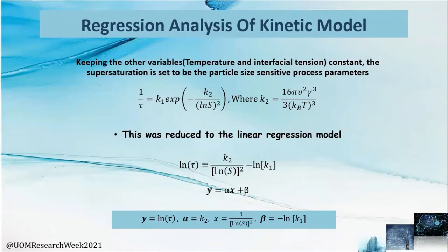For the regression analysis of the kinetic model, we kept temperature and interfacial tension constant and varied our supersaturation through precursor concentrations. We then reduced our non-linear model to a linear model mathematically, with regression constants K1 and K2 to be determined through our experiment.